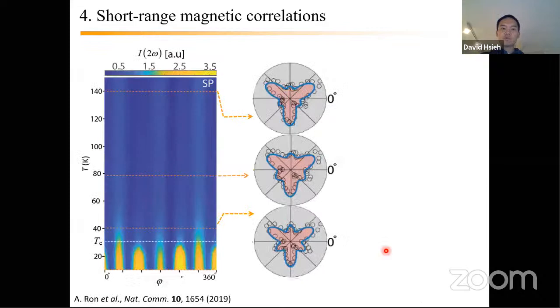So here I'm unfolding the RA patterns now. I'm plotting this on a linear axis. Here I've got my scattering plane angle phi, and here are the different temperatures. All right. So TC in this material is here, around 30 Kelvin. Something dramatic happens below TC, but even up here, in a temperature window where ostensibly nothing's going on, if you take these RA patterns, you can actually see that they're evolving with temperature. These are all, it turns out, electric quadrupole responses, which are really weak, so there's a bit of noise on our data, but the changes are clear.